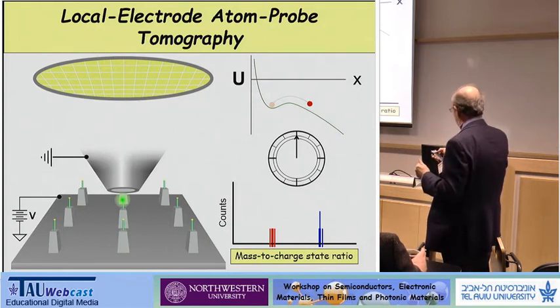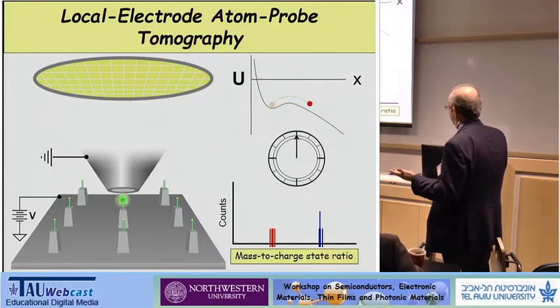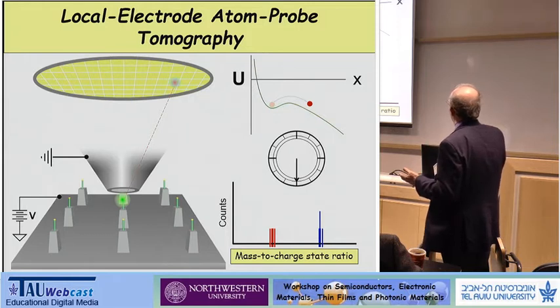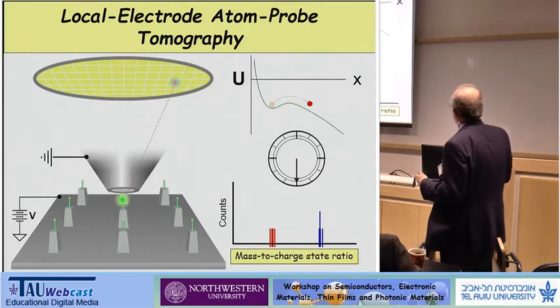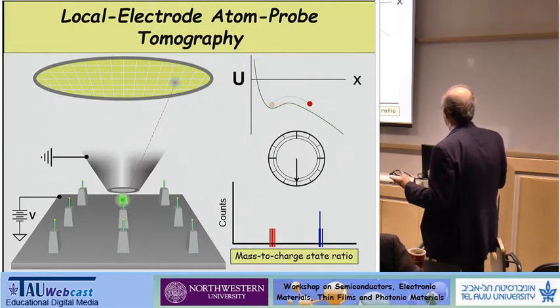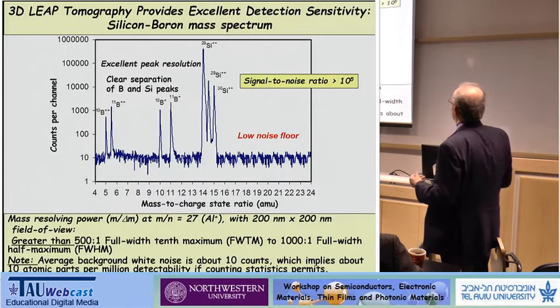This is the so-called local electrode that you're looking at here, this conically shaped device. These are silicon nanowires, say, a little bit of gold on the top, the gold catalyst, and then you evaporate. You hit them with laser light, and you can see over here what happens. This is the potential energy of an atom at the surface, and it's field evaporated over this Schottky hump, and it becomes ionized. And then you collect the mass spectrum. Every time it hits the detector, the output is a mass-to-charge state ratio, and you count and you can identify the isotopes.